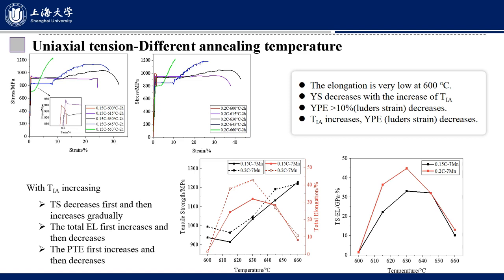It is clear that the steel shows a very good microstructure combination for certain heat treatment conditions. Here, we can see the best intercritical annealing temperature is preferred to be 630 degrees C. In this case, the elongation is very low for the 600 degrees C intercritical